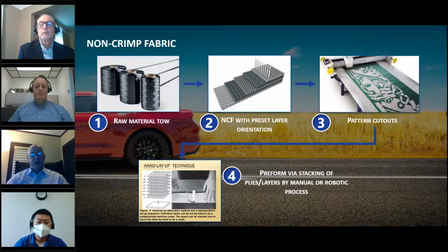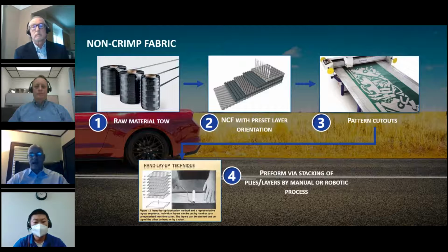In discussing preforms, let us evaluate the current value chain. If we evaluate the current value chain for the production of molded composite articles from continuous fiber reinforcements, we see that either a fiberglass roving or carbon fiber tow, or both, are used to produce an NCF or other broad good technical fabric with a preset layer orientation. The ply patterns are cut from the broad good fabric and stacked either manually or automatically in the necessary ply or layer orientations. As you can see from this process, it results in significant waste in cutting the patterns from the broad good and allows errors in the stacking of the ply patterns and schedules. Waste can be as much as 20 to 50%.